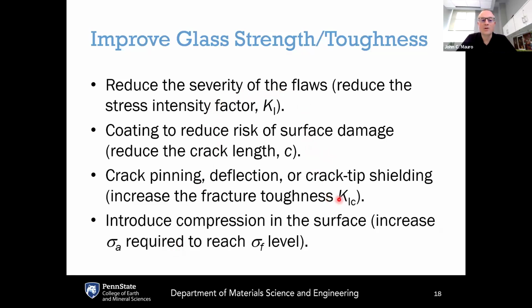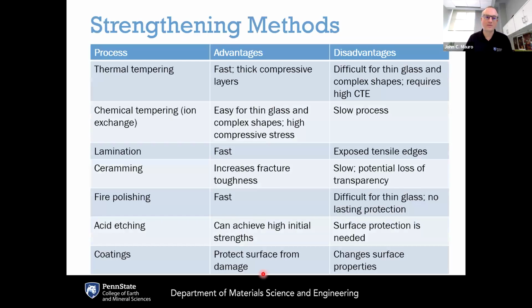Another would be, how could we increase the fracture toughness? How could we increase the K1C of the material by crack pinning, deflection, or crack tip shielding? Or could we introduce some sort of compressive stress at the surface to increase the applied stress that's required to reach the sigma F level? So in other words, could we reduce K1, increase K1C, reduce C, or increase sigma F? All of these are pathways to improving the mechanical performance of the glass.